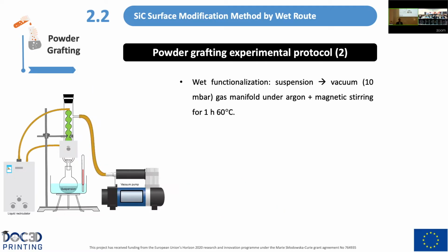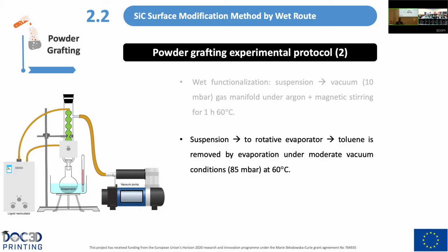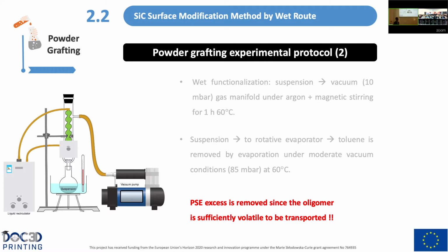Next is the wet functionalization. Here we are going to transfer the suspension into a vacuum gas manifold under argon and subject it as well to magnetic stirring for 1 hour at 60 degrees. Following this step, the suspension is again transferred to a rotary evaporator, and here the toluene is removed by evaporation under moderate vacuum conditions at 60 degrees. And after this step, we can obtain our silicon carbide as a dry powder again. But if we are using some excess of polycarbosilane, it won't be a problem because it will be removed, since the oligomer is sufficiently volatile to be evaporated.